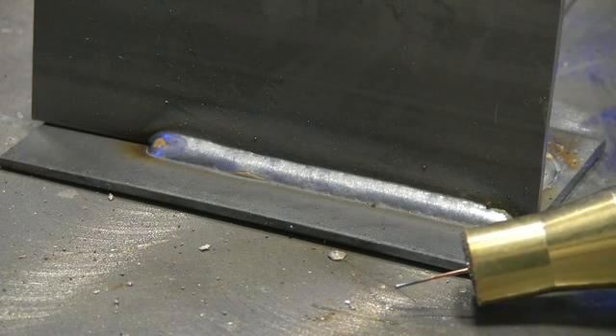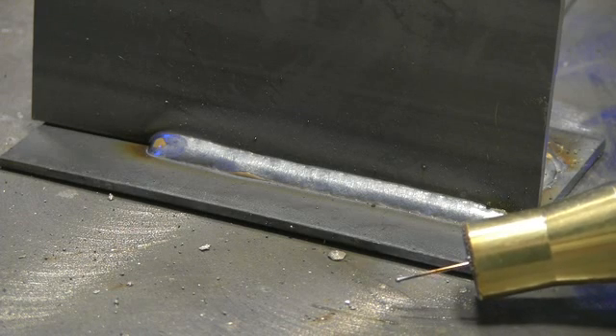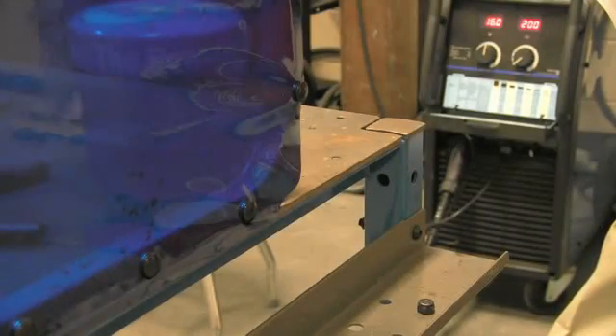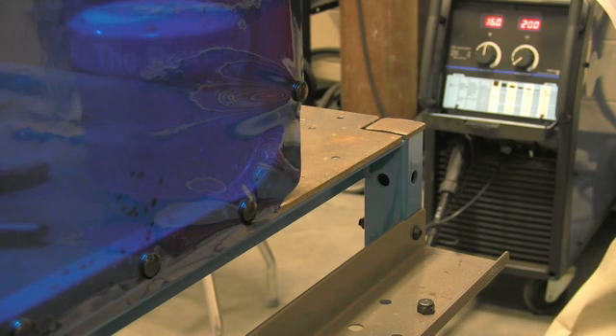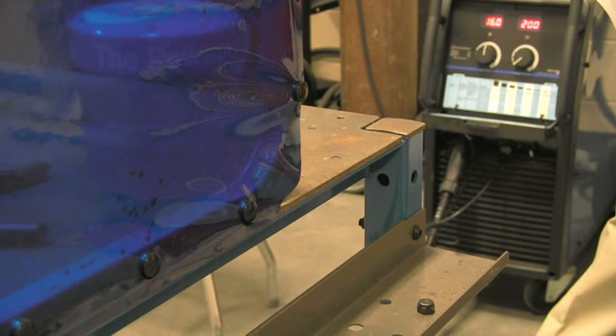But most importantly, we could tell by the sound of the arc. And so we ended up at 16 volts and 200 inches per minute. So now that we had it set at 200 inches per minute and 16 volts, we were able to achieve a nice stable short circuit transfer. But some of the pushback that we might get with that set of parameters is that's awful slow. And it's true, that is a very, very slow set of welding parameters for eighth inch material. We can actually increase that quite a bit and still maintain short circuit transfer.